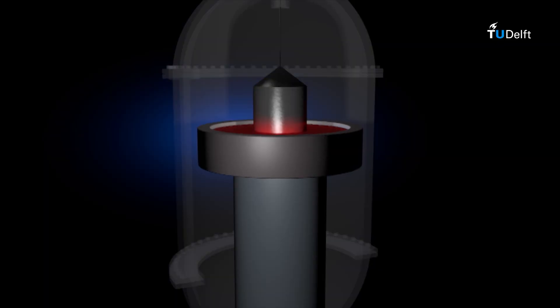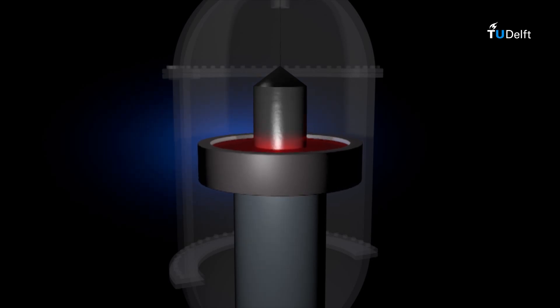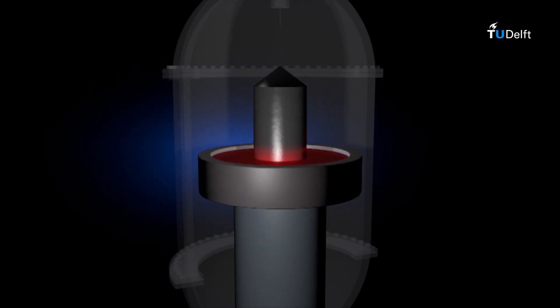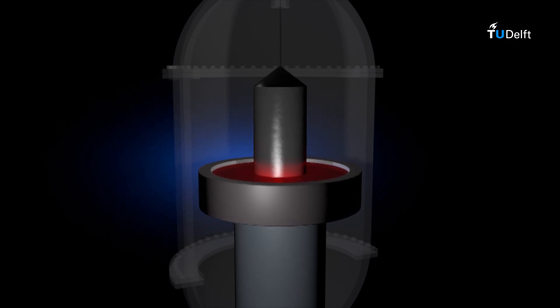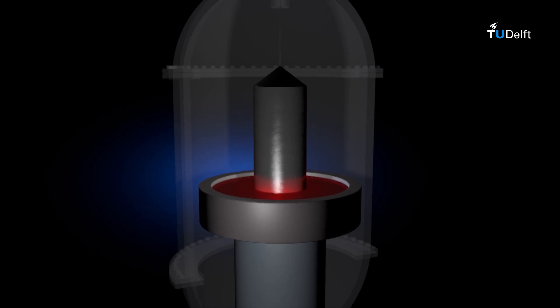In this process, the temperature gradients, rate of pulling up and speed of rotations are precisely controlled. This process is further developed through years of advances and, nowadays, crystal ingots of diameters of 200 mm and 300 mm with lengths of 2 meters can be processed.